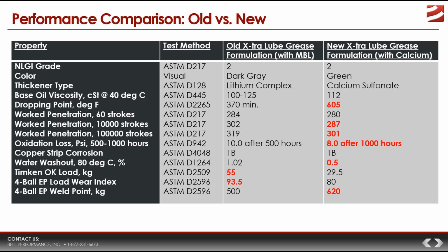The Timken load test, sometimes referred to as Timken OK load, most closely matches the traditional friction brake machine test you might see referenced. In executing this test, you have a standardized bearing, a Timken bearing, rotating at a high speed, and it's brought into contact with a steel block that has a load applied to it. The load is constant and standardized so you can control how this test is run. It's in contact with it, and they're flooding the contact area with lubricant.